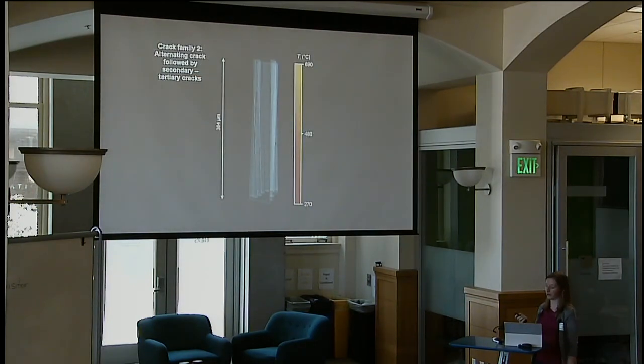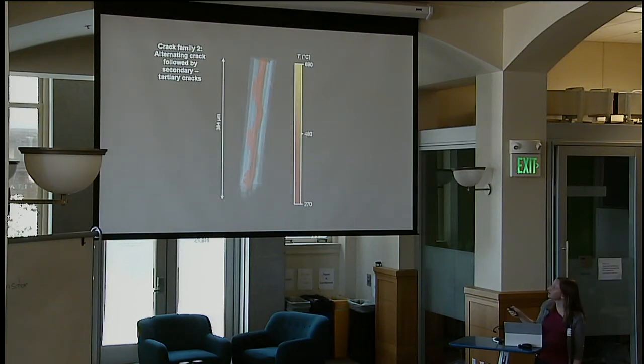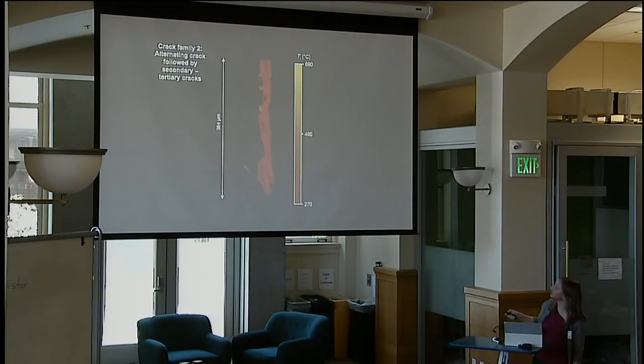So the second crack family has a different type of primary crack. These are alternating or wavy in nature. So again, first orienting you to the fiber region. This is a relatively small region of matrix between the fibers. So the first crack to form in this region is an alternating crack. So these initiate at the interface, and then they actually propagate back and forth along the fibers. And then at higher temperatures, we can see these secondary, tertiary cracks branching off of this alternating crack, and then at even higher temperatures, these interfacial cracks.